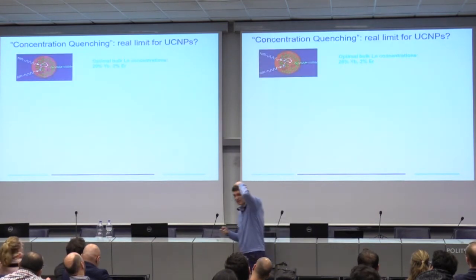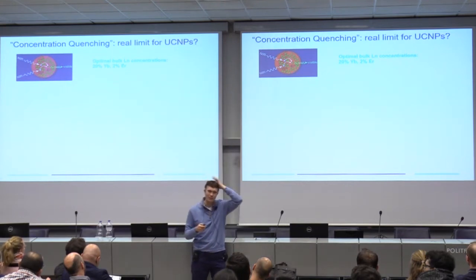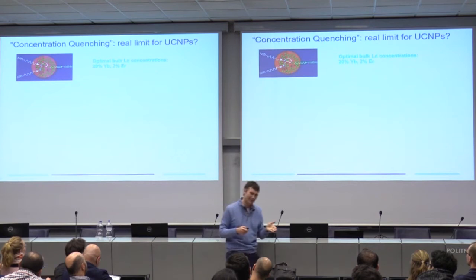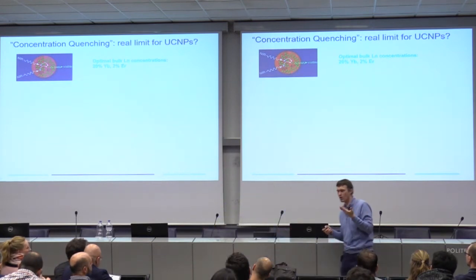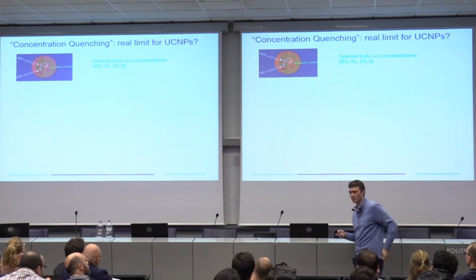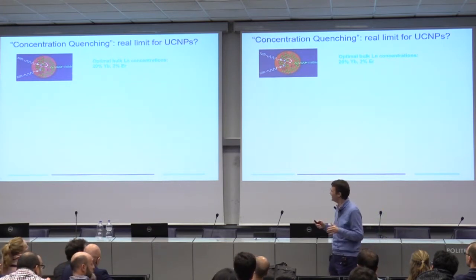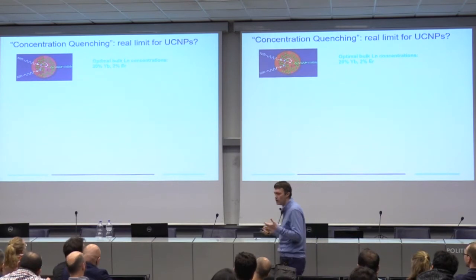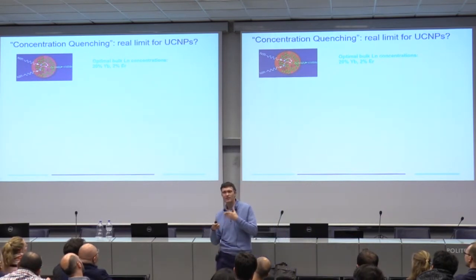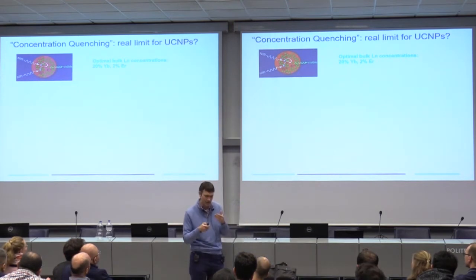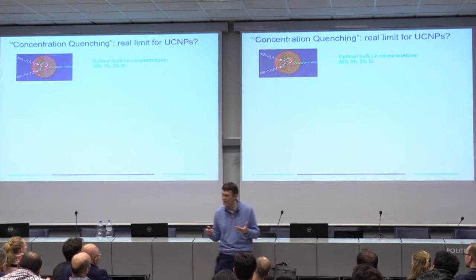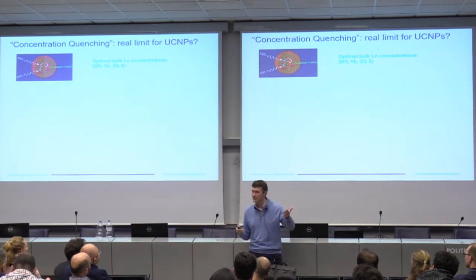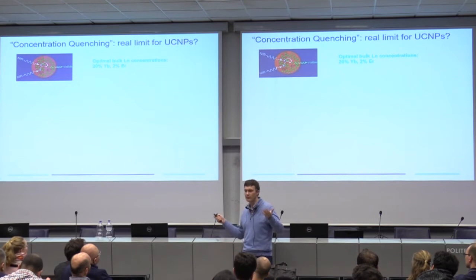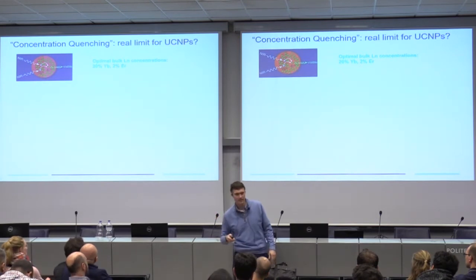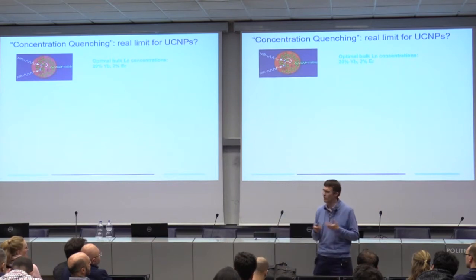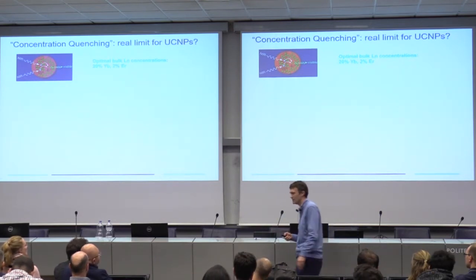If you were to ask anyone that developed lanthanide-doped ceramics before, they would say, no, can't do that. It's because you run into this problem of so-called concentration quenching. But then you ask what concentration quenching means, and things get fuzzy. What people do know from working with bulk materials is that there is very much a canonical composition. The brightest bulk upconverting materials are crystals that are doped with 20% of ytterbium, right? This is the absorber. And then 2% of your emitter, usually erbium. Erbium turns out to be the brightest. People here are familiar with erbium lasers, for example. This is the composition that they tend to use to make them.